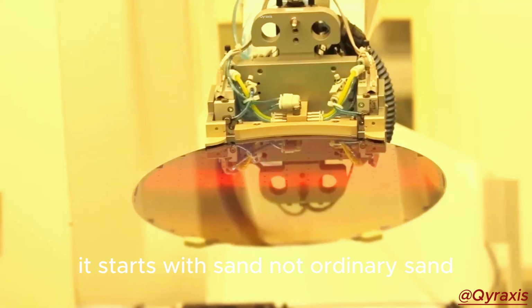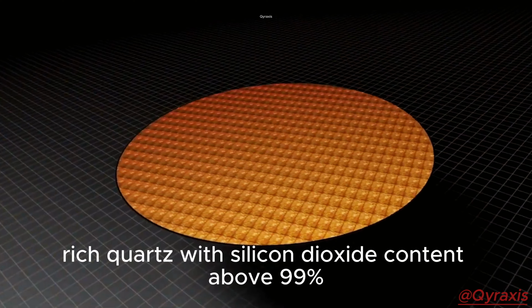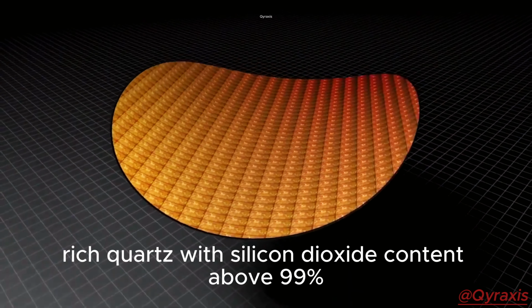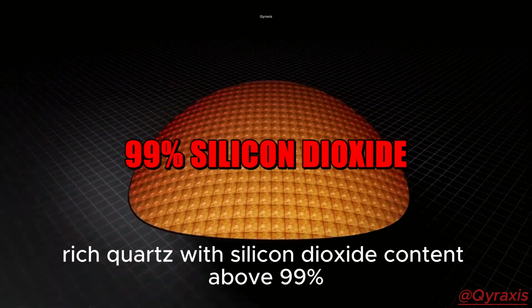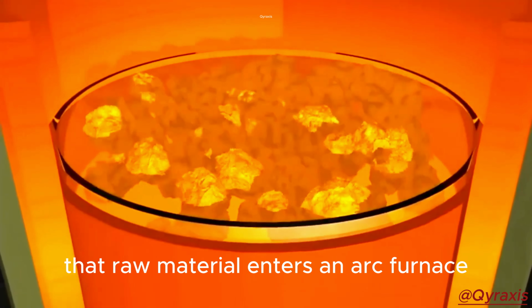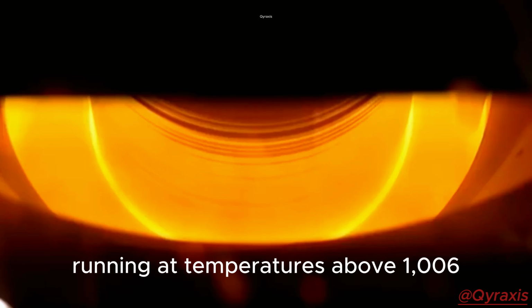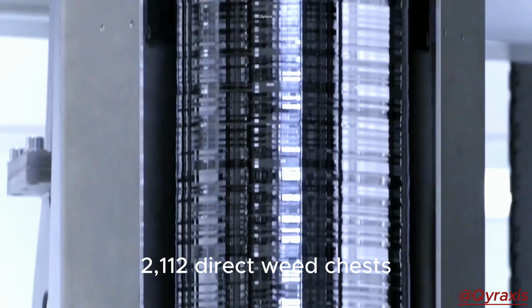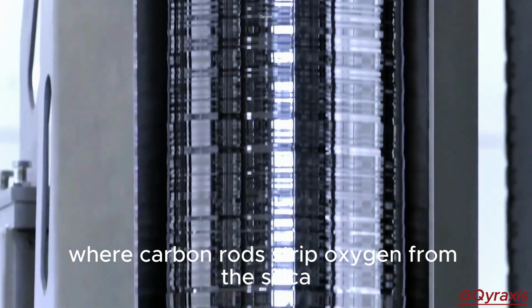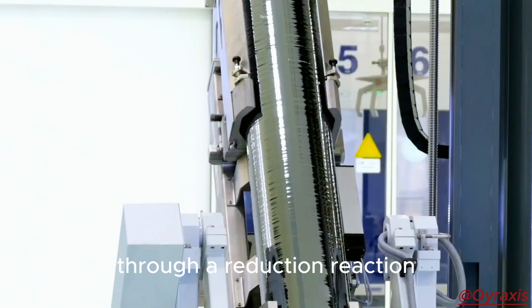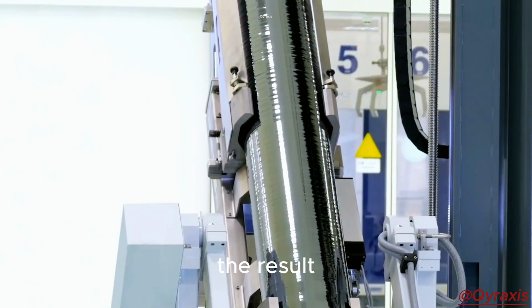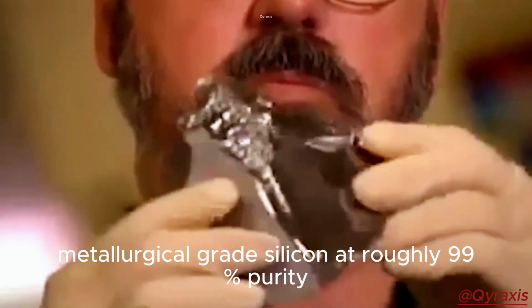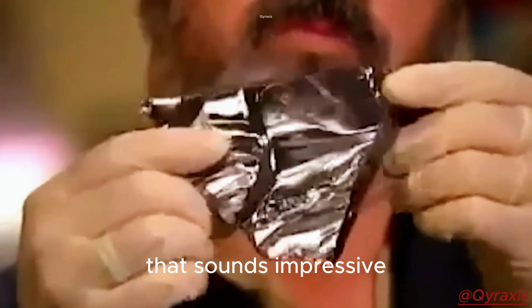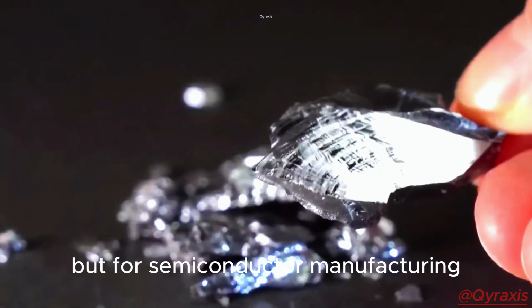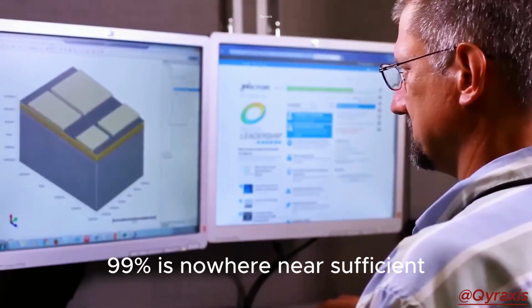It starts with sand, not ordinary sand, but silica-rich quartz, with silicon dioxide content above 99%. That raw material enters an arc furnace running at temperatures above 1,600 Celsius, 2,912 Fahrenheit, where carbon rods strip oxygen from the silica through a reduction reaction. The result? Metallurgical-grade silicon at roughly 99% purity. That sounds impressive, but for semiconductor manufacturing, 99% is nowhere near sufficient.